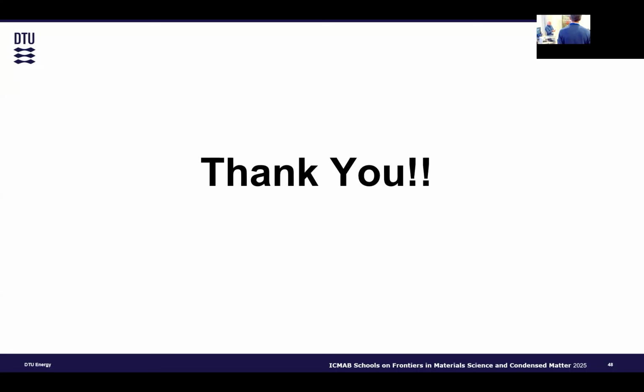I can maybe answer this question. All right, then I will come to the second. I will not forget the other ones. So there are two different cases. At the beginning of the talk, I talked about LAO STO. This is something else, and later in the talk, I talk about STO where we put aluminum and then oxidize it. So how do we do that? We take material which we deposit onto a sacrificial layer with the polymer on top. We release it. We take this material and put it on a substrate, in that case silicon, and then we remove the polymer with acetone.